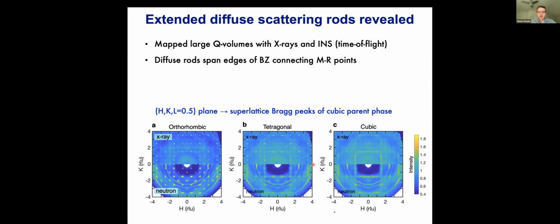And these rods partially condense when you go into the tetragonal phase at the endpoints, but there's still some rod-like signature that persists. Finally, in the orthorhombic phase, you largely have sharp Bragg peaks corresponding to all the superstructure Bragg peaks of this larger cell here, and some remaining thermal diffuse scattering. So we see these diffuse rods both in X-ray and neutron diffuse scattering. So the X-ray work was done in collaboration again with Matt Krogstad.